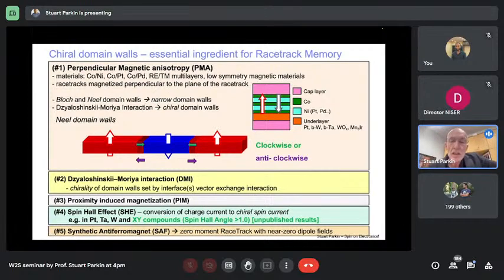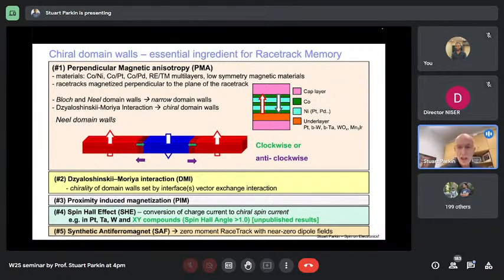Then we form what's called a Néel wall, shown by the green arrow, where the magnetization in the domain wall, as it rotates from up to down, points perpendicular to the wall. And the very next domain wall does the same thing, but because it's clockwise, the moment in the middle of the wall, shown as the green arrow, will be pointing in the opposite direction. The chirality is preserved. Now we can change the chirality by changing the nature of that underlayer from platinum to tungsten, or by putting the platinum layer on top rather than underneath. Then it would change the chirality.